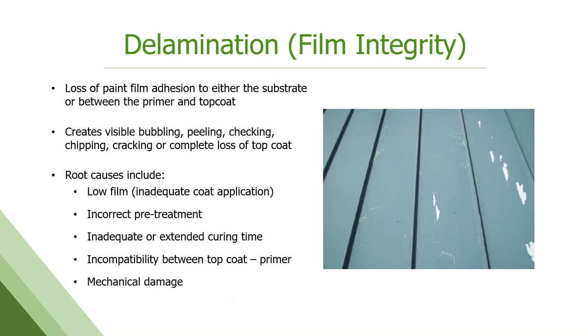Delamination, film integrity. This is a big one. This is the toughest one for those of us in my world to figure out why it failed. This is loss of paint adhesion to either the substrate or between the primer and the top coat. You can get visible bubbling, peeling, chipping, cracking, or a complete loss of paint. A lot of possible root causes for this. Could be low film, could have been incorrect pretreatment, could have been inadequate curing, could be a compatibility issue.